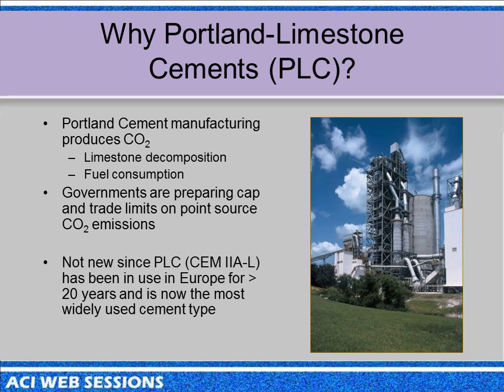So regardless of how efficient they are with their fuel, and most of the cement plants have become very efficient in process efficiency and reducing their energy and emissions from their fuel and production processes, they still have this issue that you're making a calcium-based binder. And so you break down calcium carbonate and emit CO2 in the process of making the clinker.